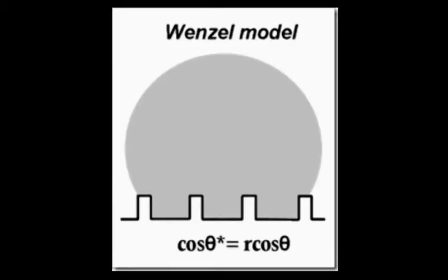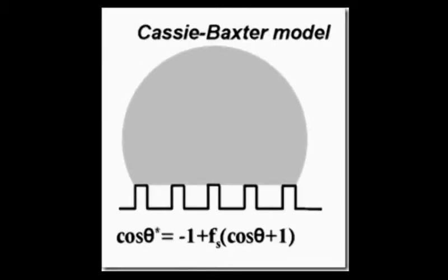For the Wenzel state, because the nanostructure increases the interaction area between the water drop and the hydrophobic surface, less actual area is needed for the thermal equilibrium. Therefore, the contact angle can be increased and the hydrophobicity can be increased. For Cassie, the situation becomes a little bit complex because the air pillow also attenuates the interactions between the water drop and the surface. But generally, the Cassie state also increases the hydrophobicity.